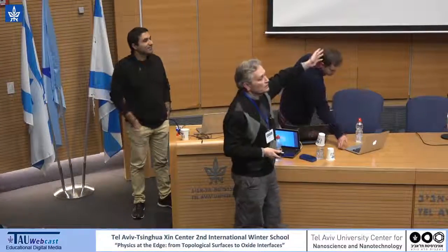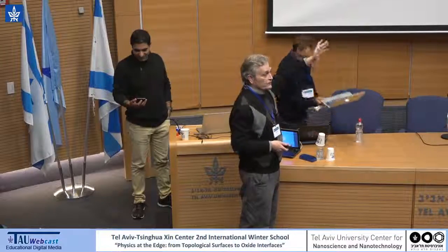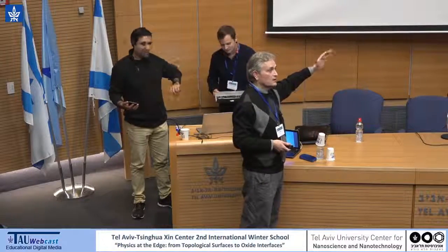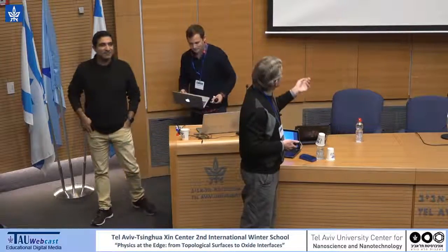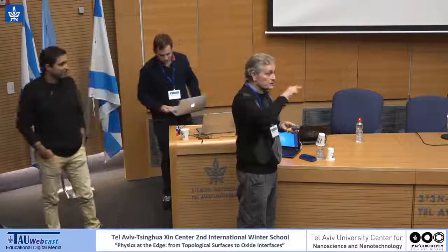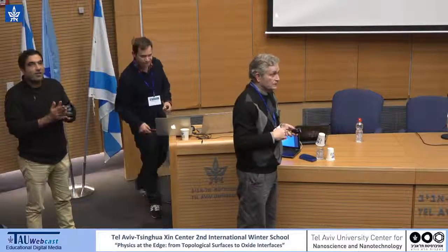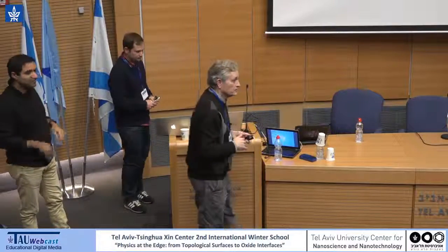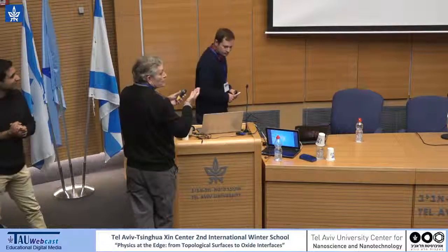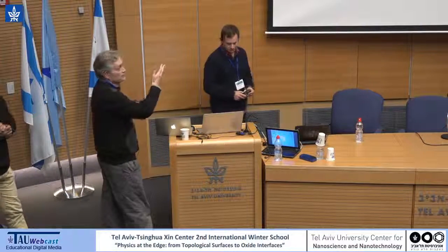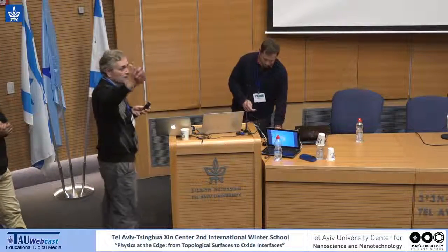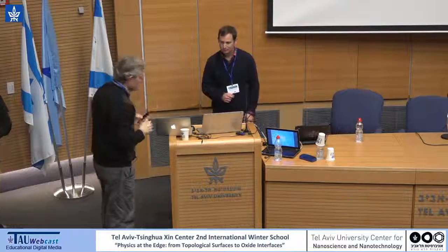Okay, so this is at 250 millikelvin. All these samples, you have to cool them to below 50 millikelvin. I don't have a slide here, but even at this temperature, we see a dip in the ρxx at the right gate. But it doesn't go all the way to 0. At this temperature, you have to go to lower temperature. But the magnetic structure, the characteristic temperature scale is many kelvins, so this is not affected.